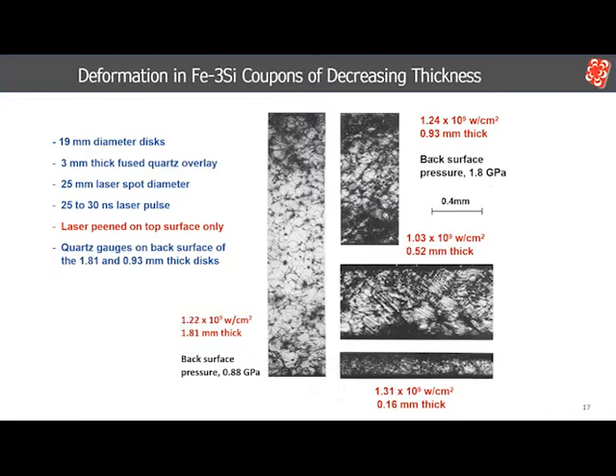Here a series of discs with decreasing thickness were all shocked with nominally the same conditions using a quartz overlay. They were shocked with a 2.5 centimeter diameter spot covering the entire surface of the discs. Although they were shocked from one side only, the back free surface shows about the same amount of strain as the front surface. There's a quartz gauge at the back surface of the two thicker discs, but not on the two thinner discs. The thinnest disc shows about 2 to 3% strain through the thickness.